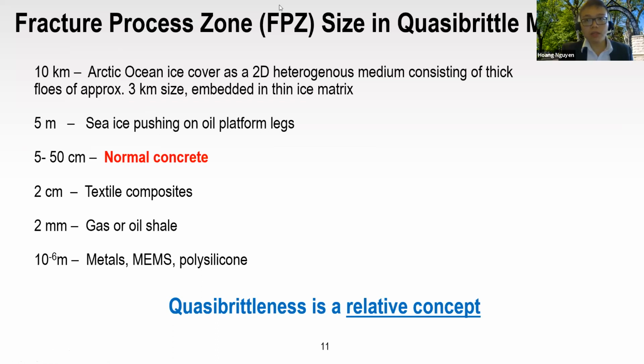For the fracture of quasi-brittle materials, one notable feature is the fracture process zone. It is the area or domain where the heterogeneity takes effect. For example, for Arctic Ocean ice, it can span over 10 kilometers. For sea ice, it can be 5 meters, and for normal concrete, because of the variation in the aggregate, it can span from 5 to 50 centimeters. For others like textile composite, it can be smaller and smaller when you consider the materials at a smaller scale. And here I want to emphasize that quasi-brittleness is a relative concept, because it depends on at which scale the heterogeneity will arise.